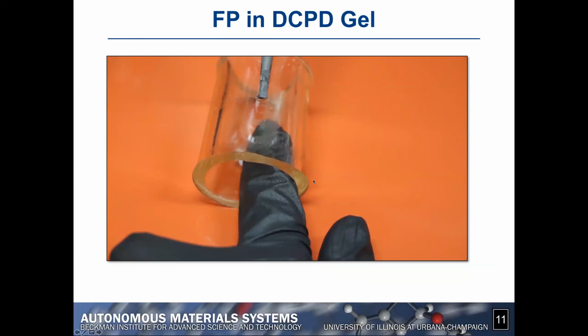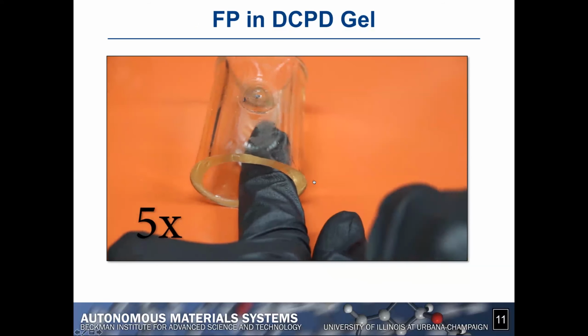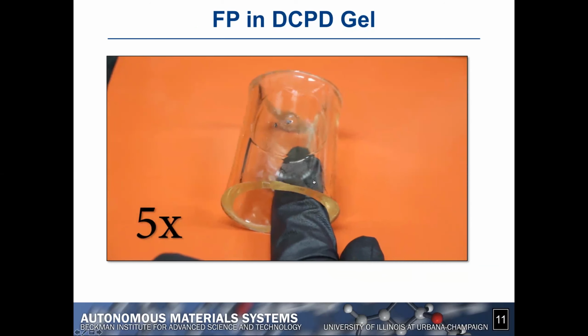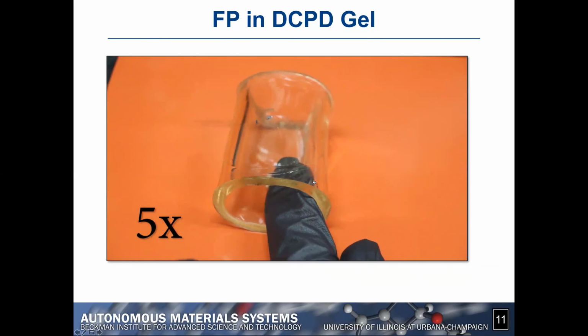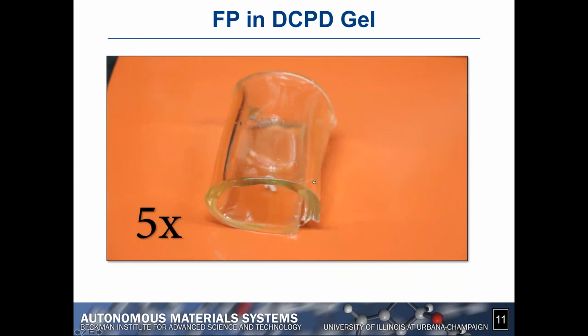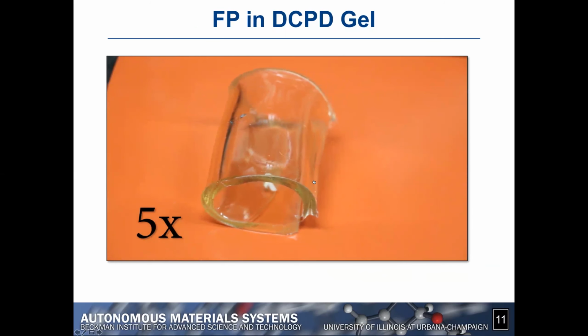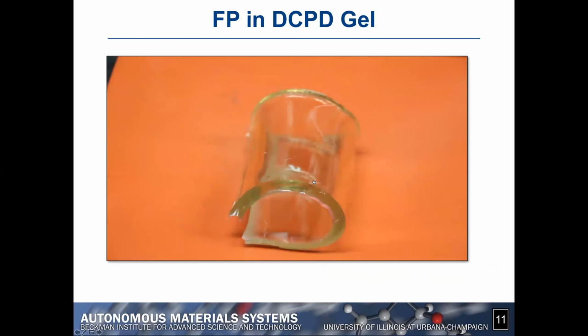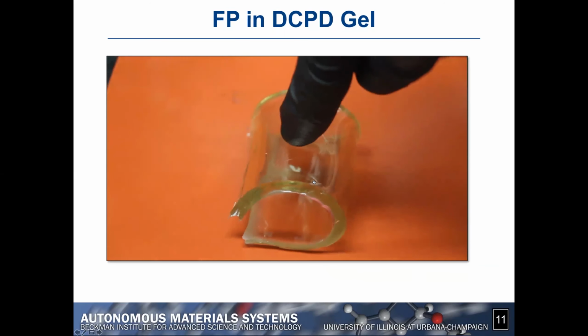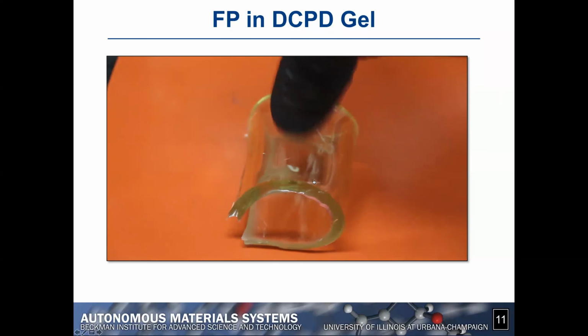And so we can also achieve this frontal polymerization in a gel. So here's an experimental illustration of a gel that has been shaped in the shape of a cylinder. And then you can see the front that propagates through the entire part. And after the front has propagated, we have a fully polymerized part, as you can see right over here. So we have a very stiff type of polymer.